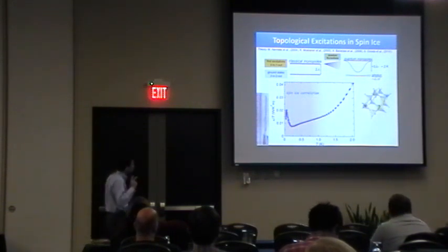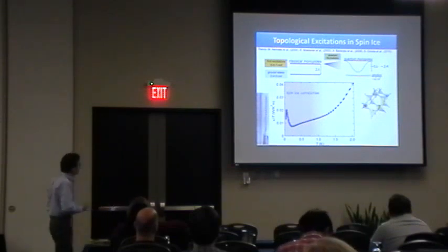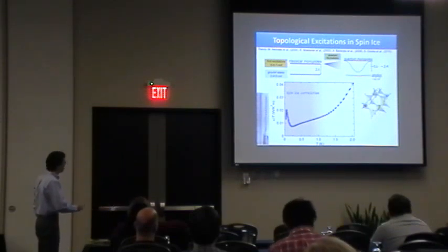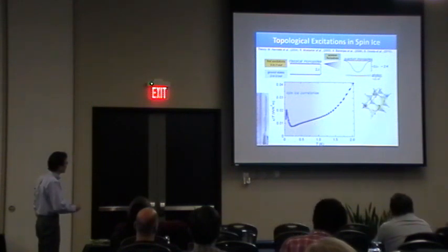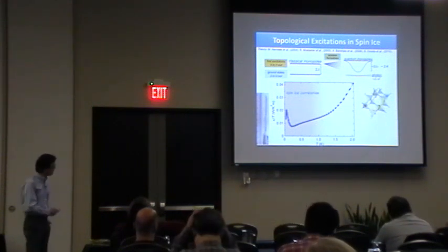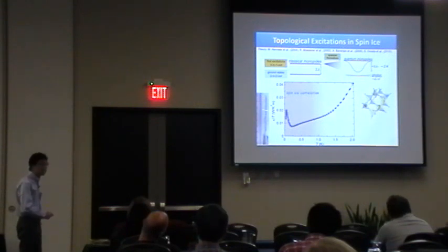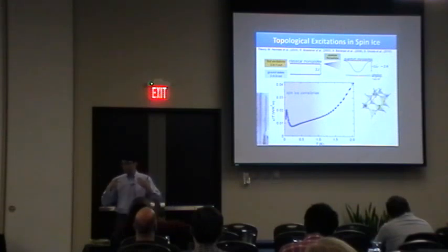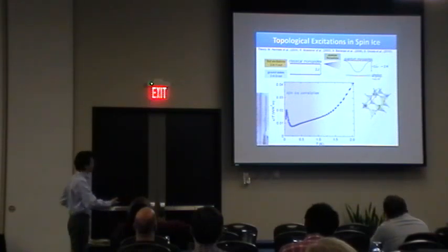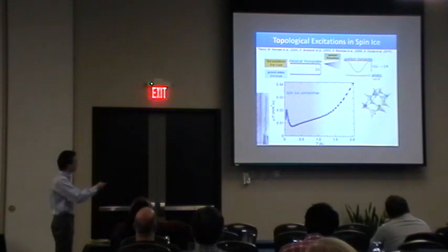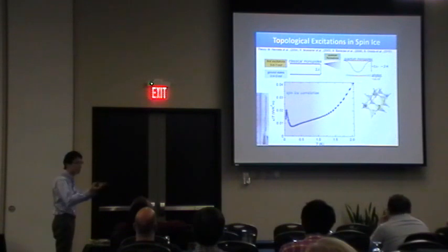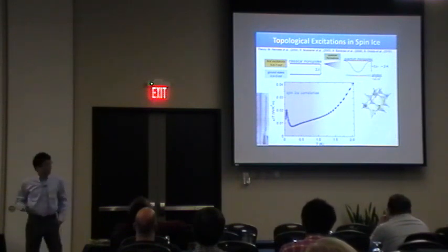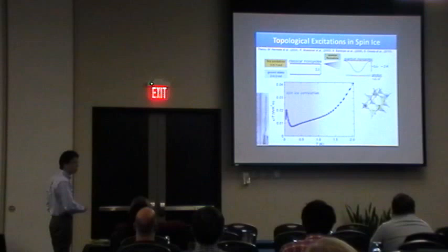And then we managed to have a fully spin ice correlated region below around a few hundred millikelvin. And suddenly we start seeing a very large increase of thermal conductivity. Thermal conductivity is the property of how these materials allow the coherent propagation of heat. So there must be a lot of fluctuation to assist the heat transport, right? The phonon does not actually exist at such a low temperature, 200 millikelvin and below, but the conductivity suddenly increases.